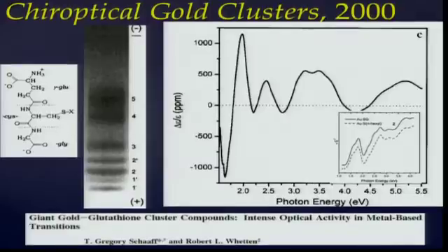And so these bands were pulled out of gel electrophoresis. Those don't require any staining because the metals are so strongly colored. And you take them out and measure their circular dichroism spectrum. And one important question people always ask is, well, is it really the same cluster? Is it really the same structure when you have a chiral ligand like glutathione or you have an achiral ligand like hexane thiolate? And the answer, as far as the regular linear optical absorption, is yeah, it's the same thing, okay? And so it's not just that chirality has selected a different structure, and I think Professor Bjørnholm showed this.